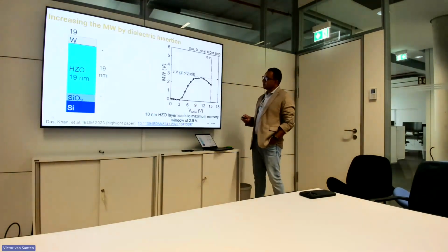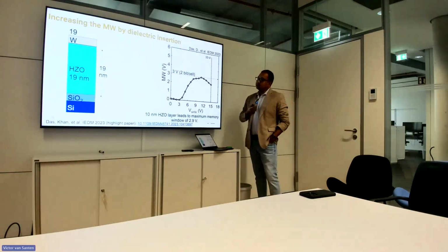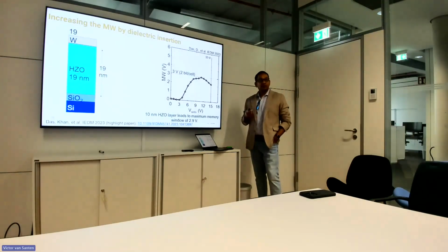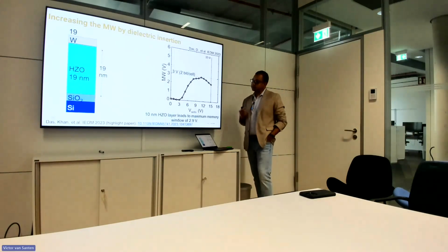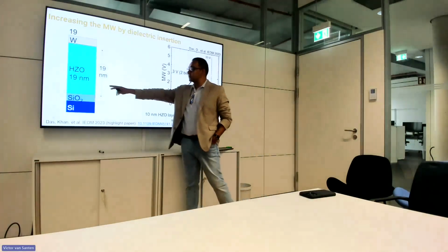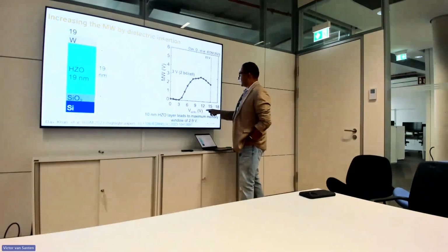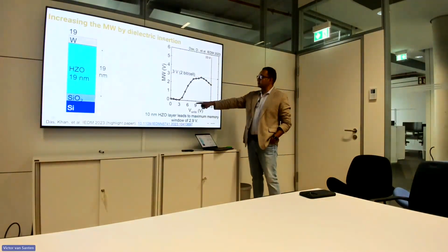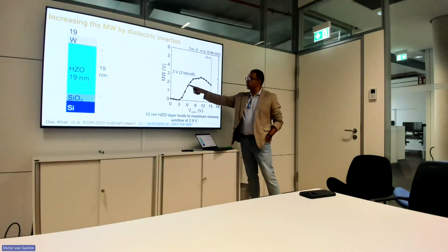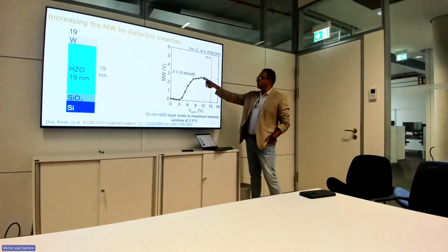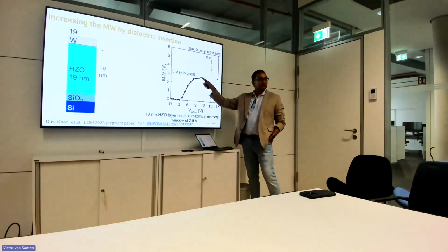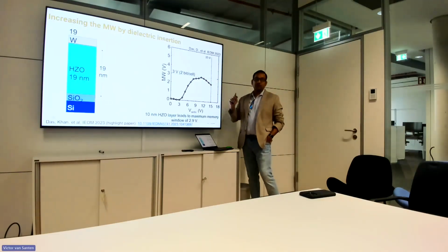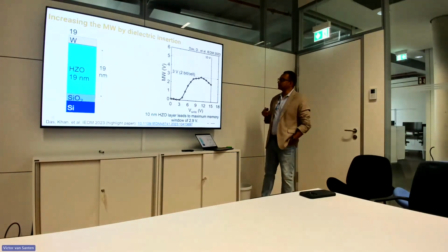Okay. So then what we did is we tried to look into how we can design the gate stack. So we took a 19 nanometer hafnium zirconium oxide layer, plotted the write voltage on the x-axis against memory window, and you can see that as we increase the write voltage, the memory window does indeed go up, but it goes up to 3 volts and then it doesn't go up anymore. We want 6 volts, 6.5 volts.